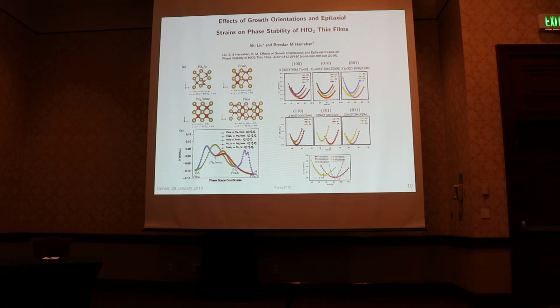The problem is you're starting out with something that's monoclinic or orthorhombic, and so that means that it matters. You can't just say like 100 or something, because maybe it's the other. You can switch A and B, and it's different. They're not equivalent. But they have very similar lattice vectors, so you can't just look at the lattice vectors and see which is A, B, or C. Anyway, one of the things that he found that's extremely interesting to me is quite a large barrier between the polar phase of this orthorhombic polar phase and this nonpolar orthorhombic phase.